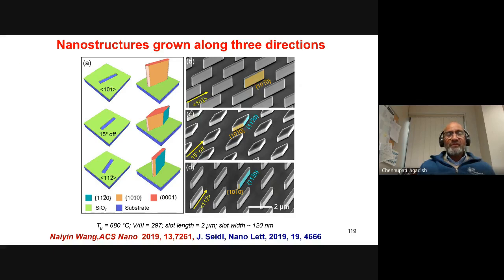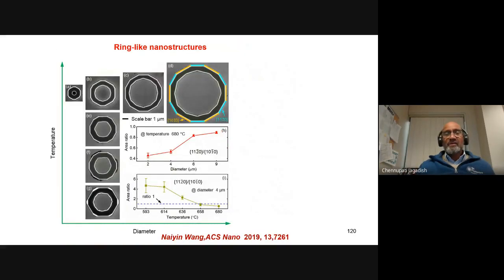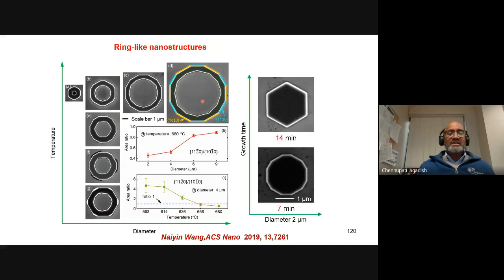If you open the slot in between these two orientations, what you end up creating is a beautiful diamond-like structure with these alternating facets of this particular one and this particular one, for example, here. So now you can see, instead of just making nanowires, we're able to really make nanomembranes and nanodiamonds and a wide variety of structures. So then we have gone off and opened the ring, for example. Again, Naiyin Wang has spent a lot of time optimizing these things.